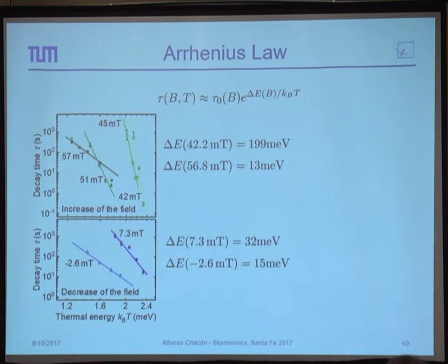These are in qualitative agreement with the predictions, which expect a strong field dependence of the energy barrier, as well as a higher energy barrier for the conical phase than for the helical phase.